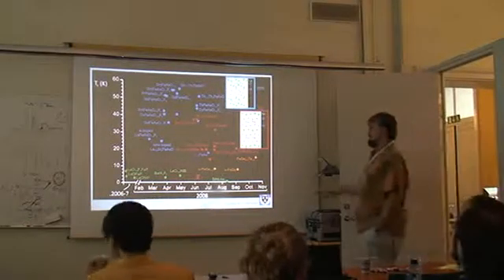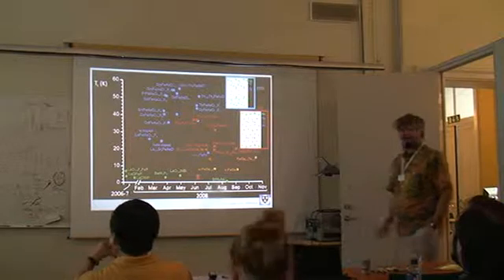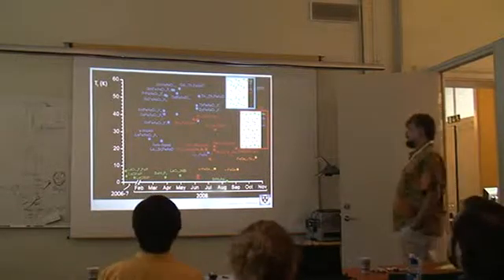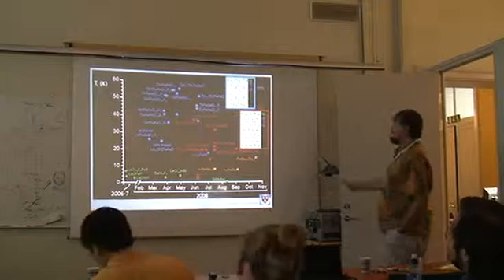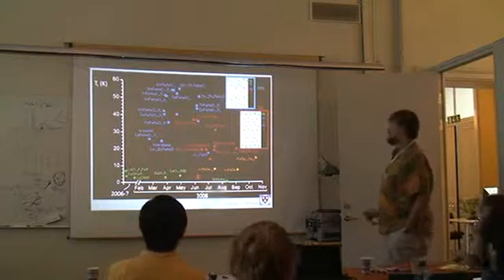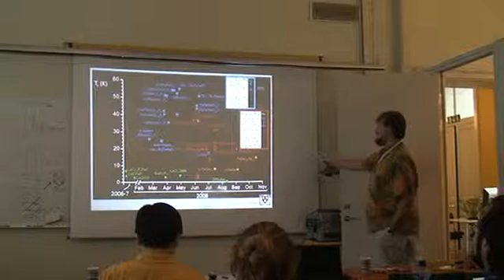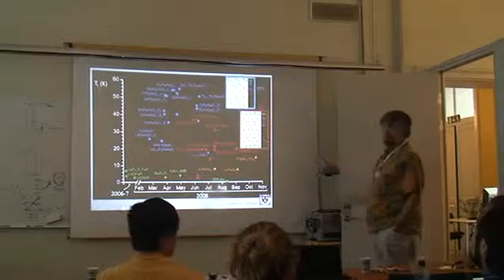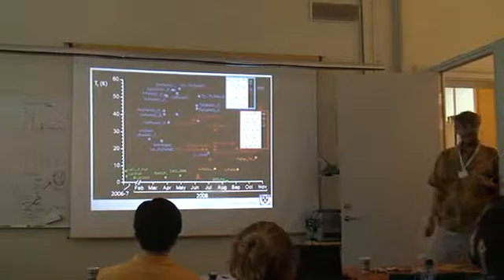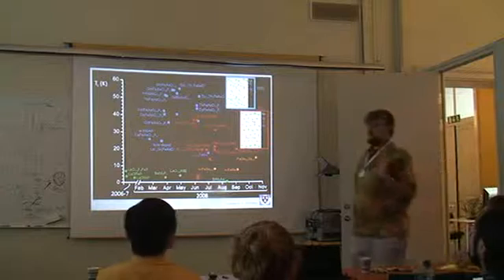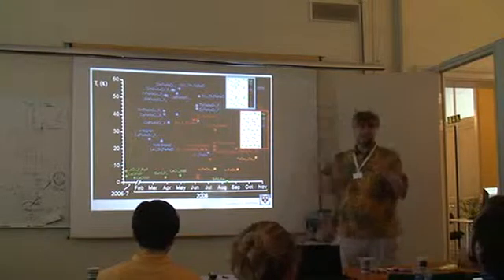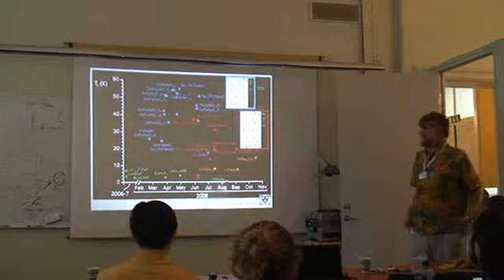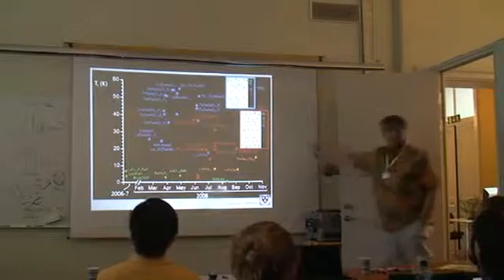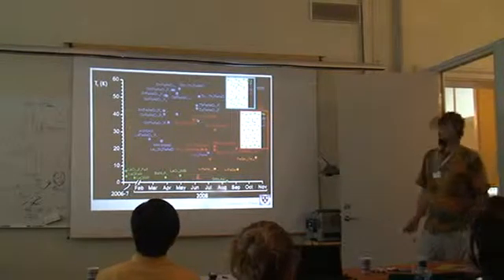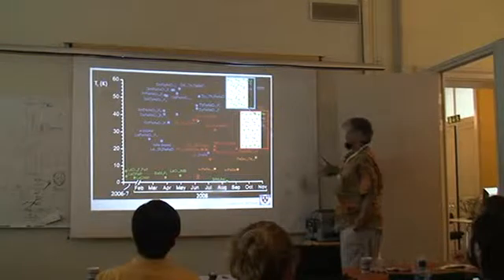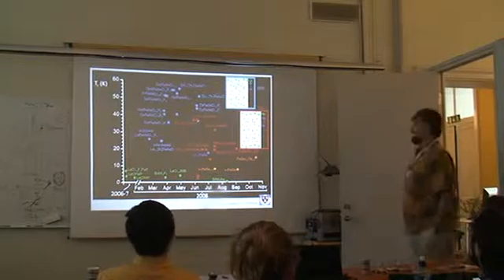is a list of about a third of known compounds. You cannot fit more on this, and I stole this from Jenny Hoffman. And this shows 2 basic, most interesting structures. 1111 already mentioned, and 122. This 122 material has TC of about 38 or so Kelvin, and its main significance is that one can make very large, very good single crystals. So lots of modern experimental work is done on 122. This is a record holder with about 58 Kelvin transition temperature, but it's quite difficult to make single crystals. There are some single crystals, but they're not easy to make.